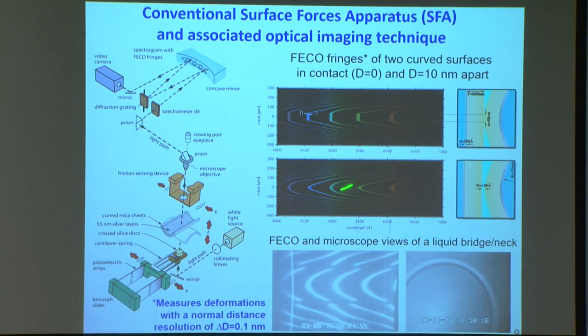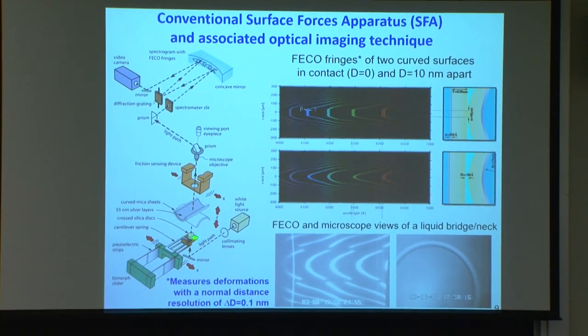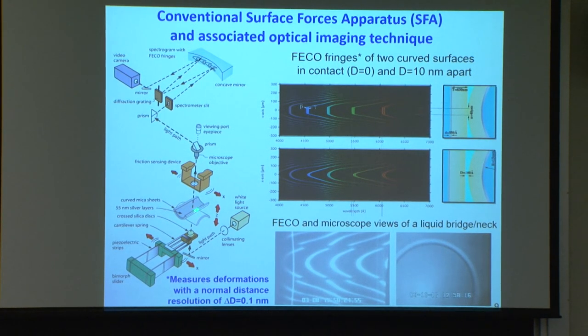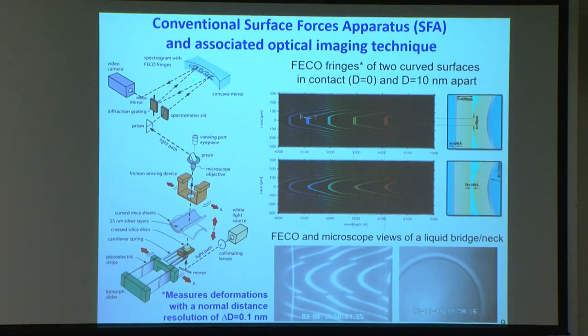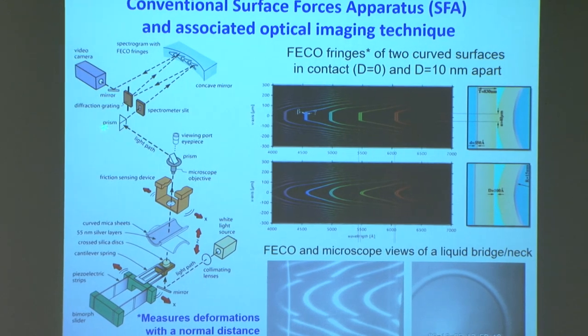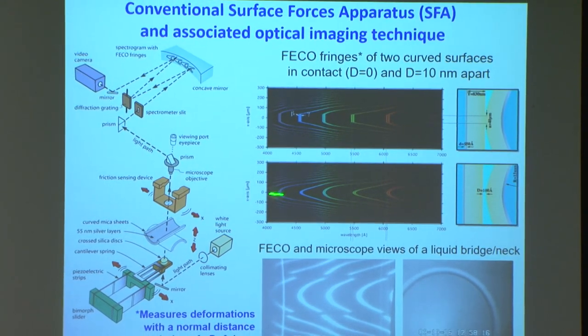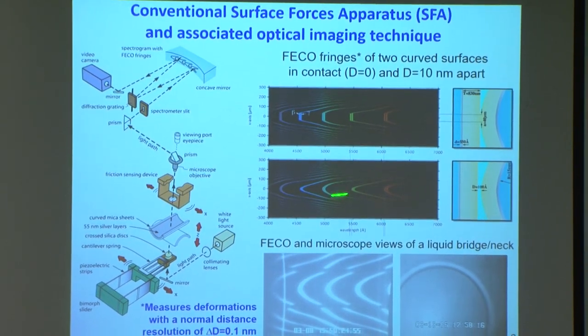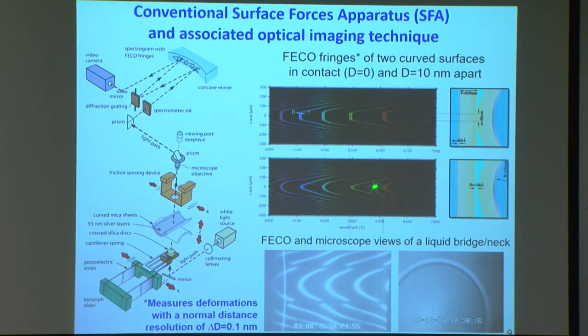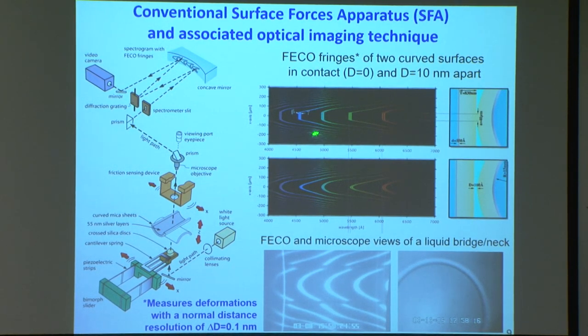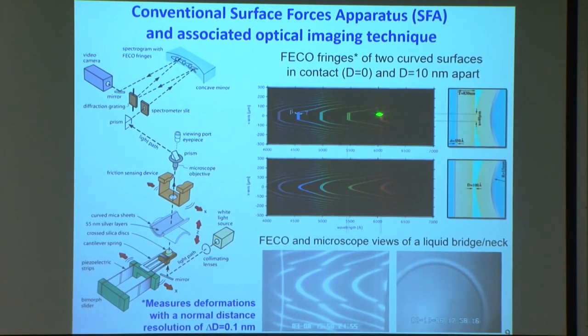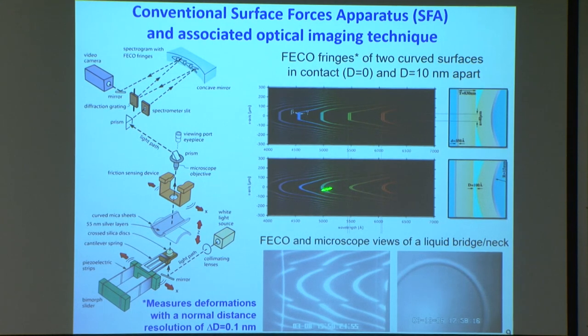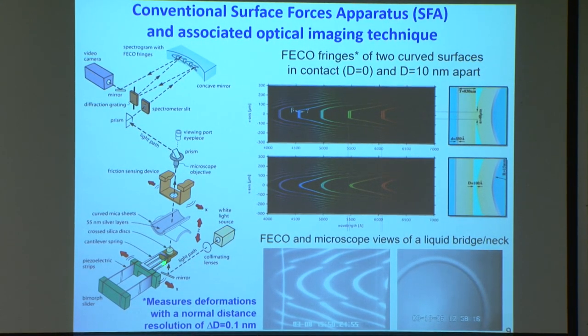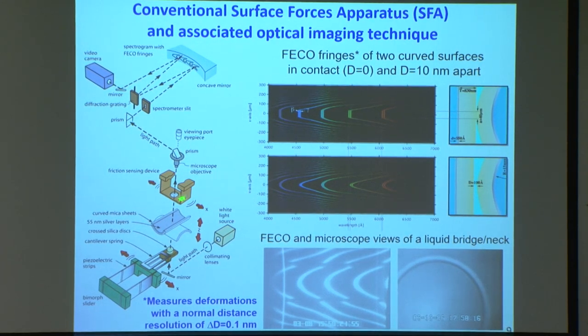This picture shows what happens when you pass light through the surfaces, and this is white light, and the surfaces often are just cross cylinders, locally a sphere, like a sphere on a flat, and then the light goes to a spectrometer, which separates the different wavelengths. So if you have curved surfaces, you see a series of fringes. I won't describe the details, but these are well-known fringes that reflect the shapes of the surfaces. And when the surfaces are brought together, the fringes move to shorter wavelengths, and then when contact occurs, you get a flat part, and that gives us the shape of the surfaces. The flat part is the contact area or radius, and one can measure this to about an angstrom, and one can then measure forces by measuring the changing deflection or the stiffness of springs, and one can move surfaces laterally and measure friction or lubrication forces.